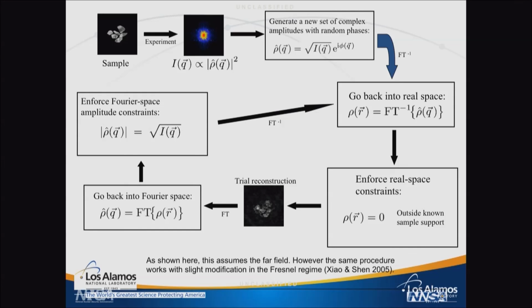So you can go and enforce those constraints, such as setting the density to be 0 where you know that it has to be 0, and then re-Fourier transform that back into Fourier space, and that will now make a prediction of both amplitudes and phases from that object. You replace the amplitudes with what you measured, but you keep the phases that you calculated here, and you go around again and again and again, and it converges. It's been proven that except for mathematically weird circumstances, it will always converge, I've been told. I'm not a good enough mathematician to understand the theorem, but it does actually converge.